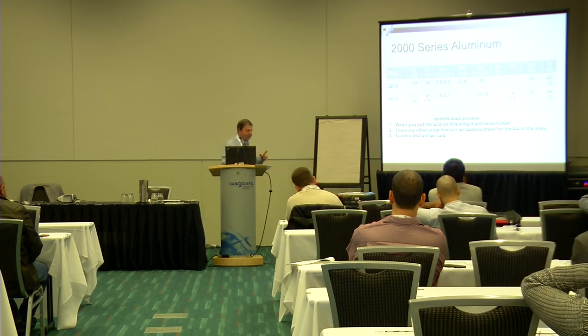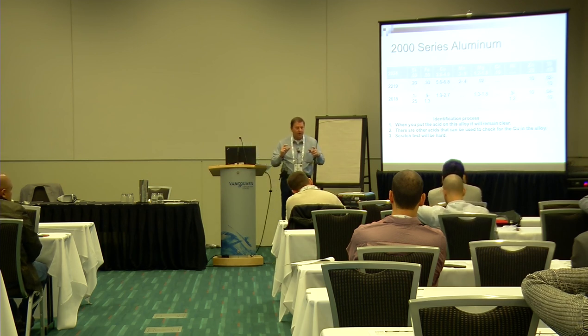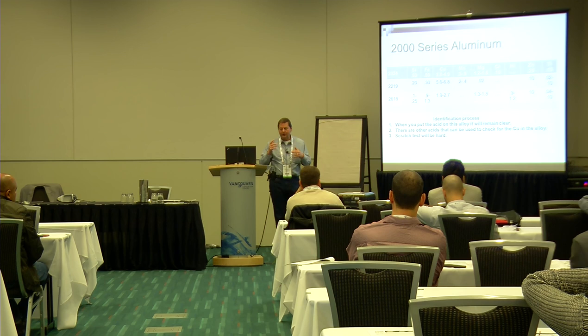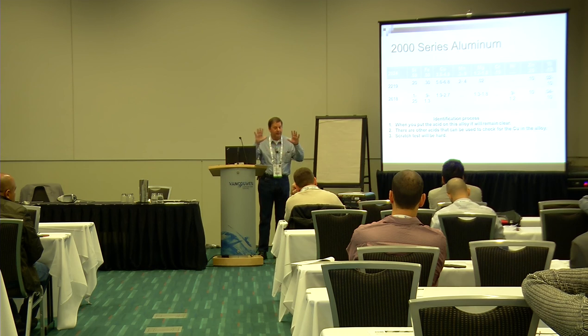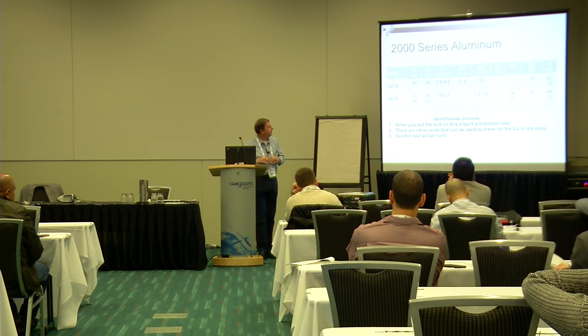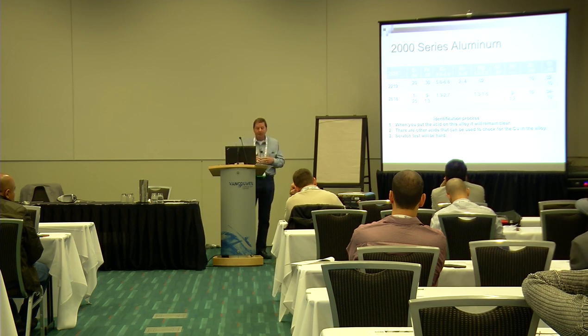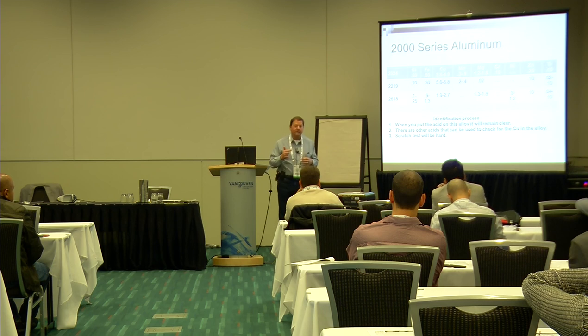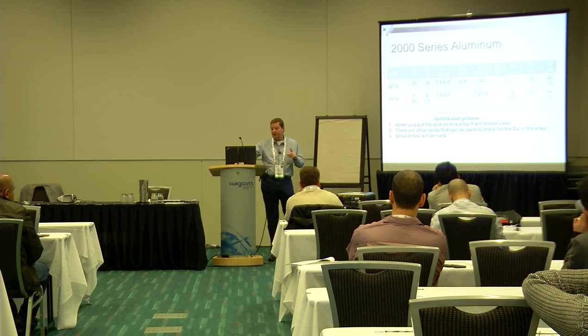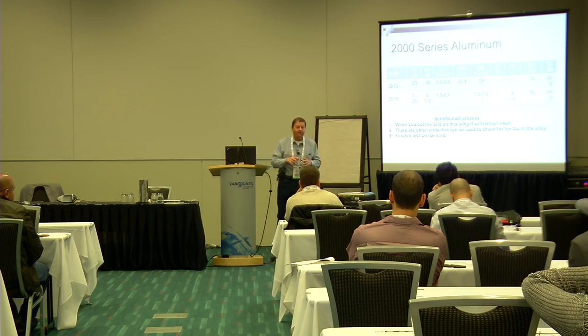Remember I was saying that what you're looking for in all these alloys is what is it that stands out? So remember, I said 2000 is basically the main element there, other than aluminum. Remember, aluminum's still going to be the majority. But look at what happens when we look at 2024, which is the one on the top. Look at the copper, 3.8, 4.9. Okay, that's huge. So when we're looking for copper on our ingot side, we can put some 2024 into the furnace, assuming it can tolerate the other elements. And now we don't have to put number one copper in.